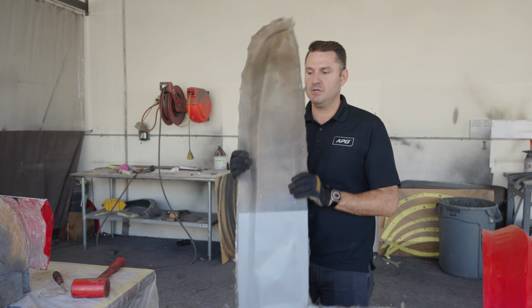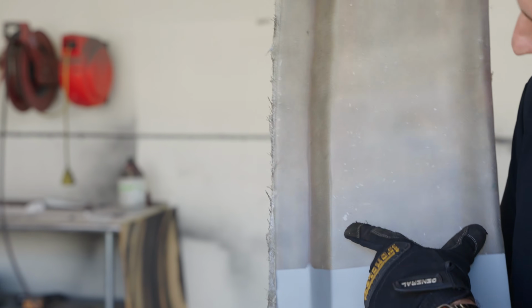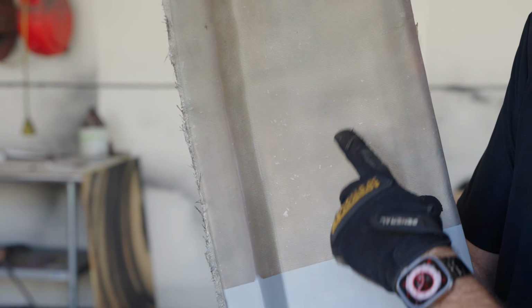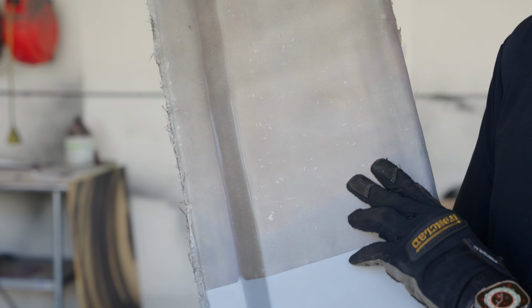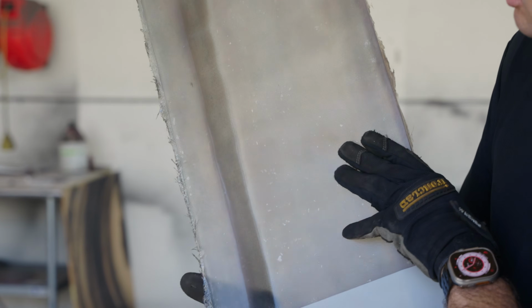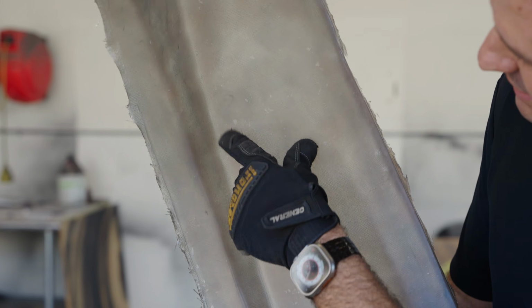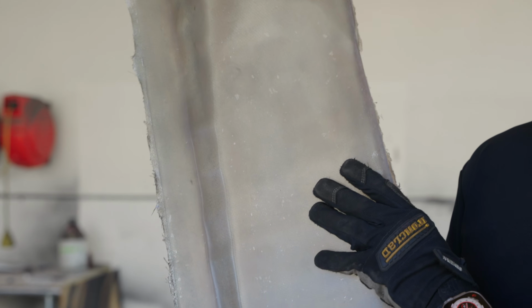So I'm bringing it in close. Each of these lighter areas are air pockets, air voids. Air is the devil when it comes to composite manufacturing. Look at this. When you see the darker areas, that's resin-rich, where it's like a pool of resin and not interweaved into the glass fibers. Corners and peaks and valleys are where you typically see the worst issues. But on this part, I would estimate there's at least 5,000 air pockets.